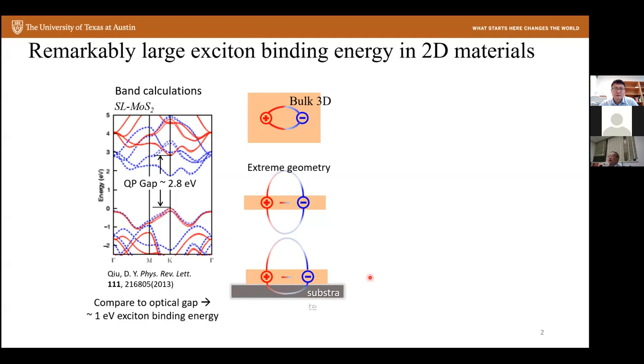But now if you think about the extreme geometry, with an electron and a hole, the Coulomb field between them goes into the vacuum. That means you have the loss of screening, and the loss of screening actually increases the exciton binding energy. Previously, the hydrogen atom has a very, very large binding energy, but it was really cut down by the dielectric environment. But once you bring it to such an extreme geometry, then this Coulomb screening is cut down tremendously.